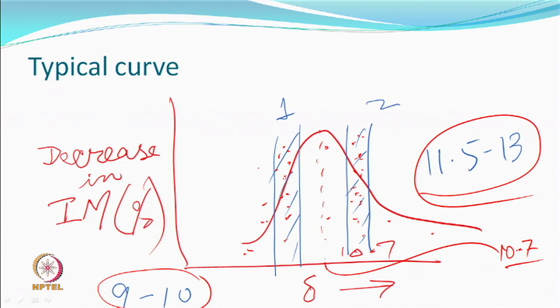So, it has got two different segments which are interesting segments. They found that solvents which are lying on this left side are more interacting with the aromatic segment. Solvent on this side interact with the aliphatic segment. So, there is complexity in trying to explain.